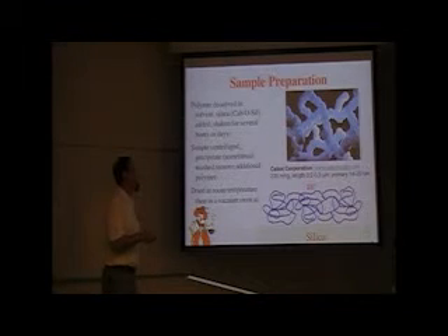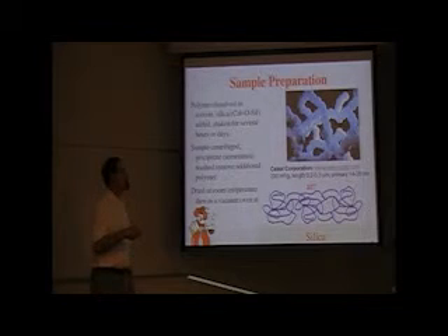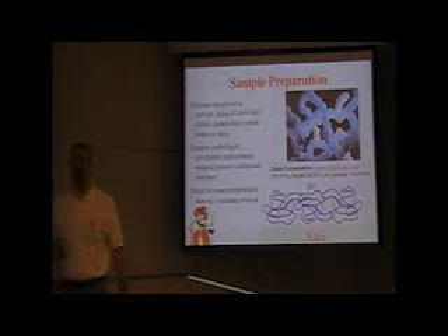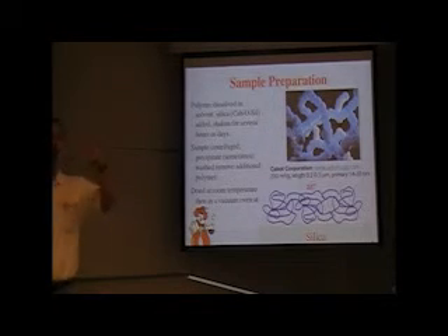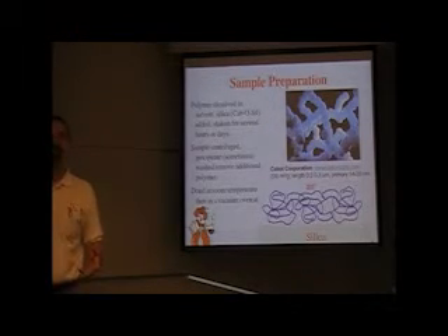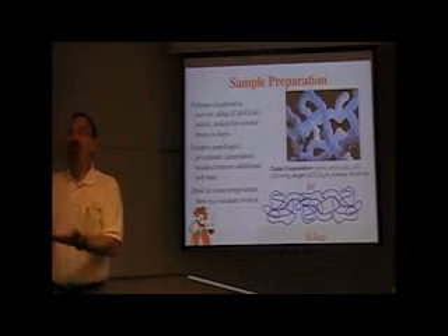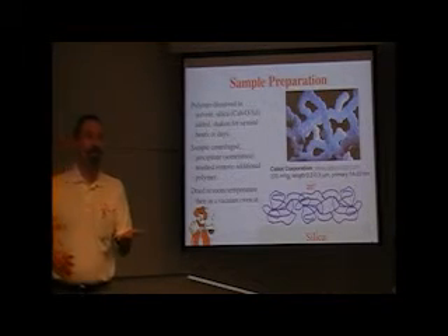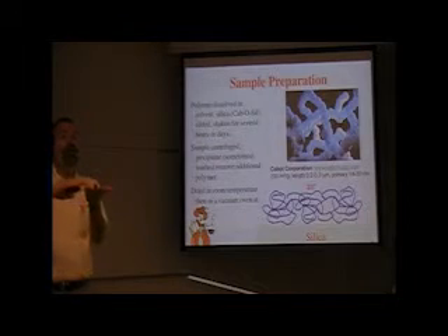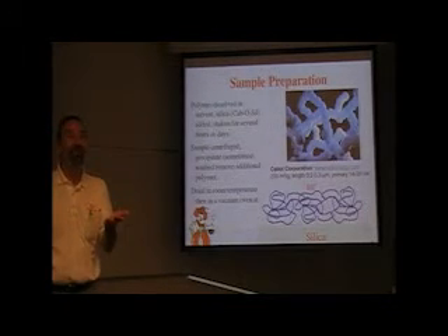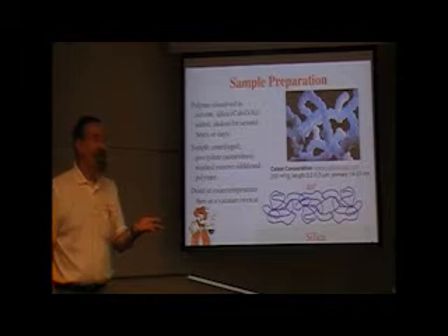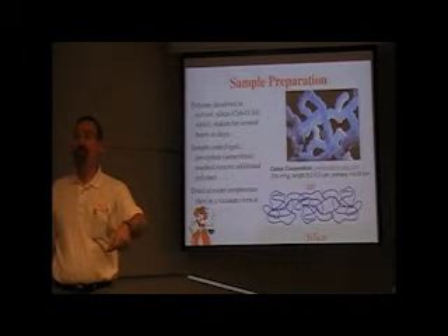Okay, so we're going to put these on. The problem is NMR is not very sensitive in some cases. So what we do is we put these on surfaces. In this case, these surfaces are little balls of silica because they have lots of surface area. The more specific surface area you have, the easier it is. Because if I take just a piece of glass, I would like to be able to do these experiments on a glass slide. But if I put a really thin coating, I'm talking about 10 nanometers or less, on a glass slide, there are just not enough of them in there.